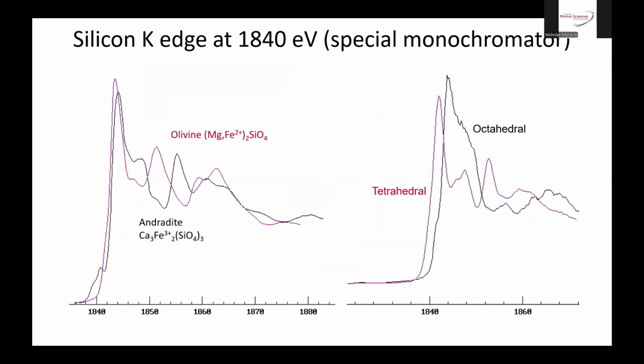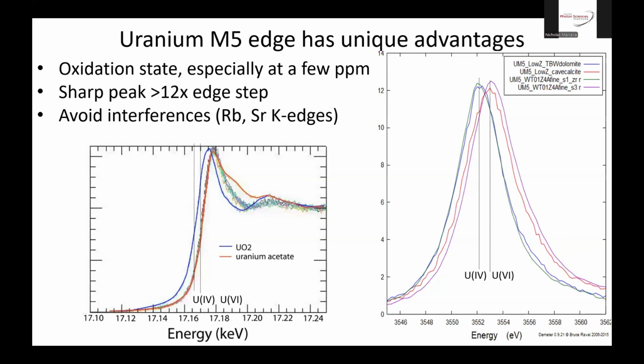Silicon, again, these are all the same oxidation state, but the silicon K edge requires a special monochromator crystal to reach, but we hope to be able to do that as well. But again, it shows a lot of differences in structure, small features, peak position, with different chemistry and different structures, and also different coordinations. And for a heavier element, okay.